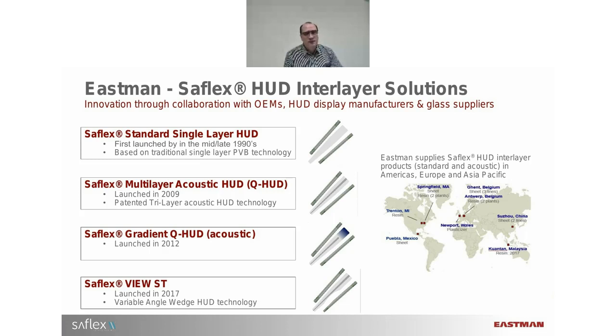So Eastman has been playing in this market from the beginning, starting to try to align the two images, because if you project on a glass and you have a double glass windshield, you have two projection screens, so you will see two images. If you don't take any precaution, you will see both images, what we call a double image. So Eastman introduced a PVB, an interlayer to glue the glasses together, where the thin side is on the bottom and it's growing in thickness towards the top. And the purpose is there to align two images. So still the two images are there, but the driver sees only one because the two images are nicely aligned.